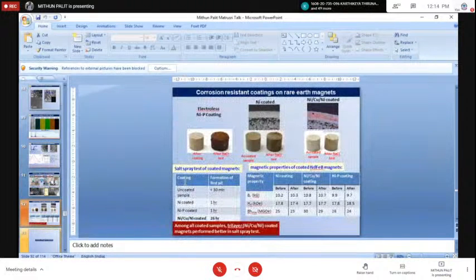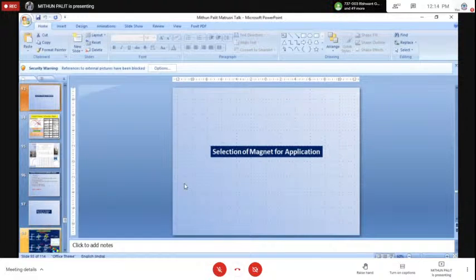So another method we found is that we can do these things even using some vacuum packing. So there is no restriction with shape, no restriction with size, so unrestrictedly we can increase the scale of operation. All these magnets are also reactive, because the rare earth has reactivity. So we have developed some coating also for this magnet. These nickel, copper, nickel tri-layer coatings are very efficient to protect these magnets from the environment. So we are ready with the upscaled magnet.